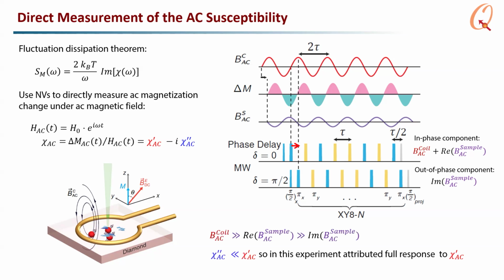So it turns out there's some hierarchy of sizes of these fields. The coil field is much bigger than the real part of the sample field, which is much bigger than the imaginary part. So it's pretty tricky to get out the imaginary part. This is solved in classical SQUID measurements by doing the two counterwound loops. We can't do that here.